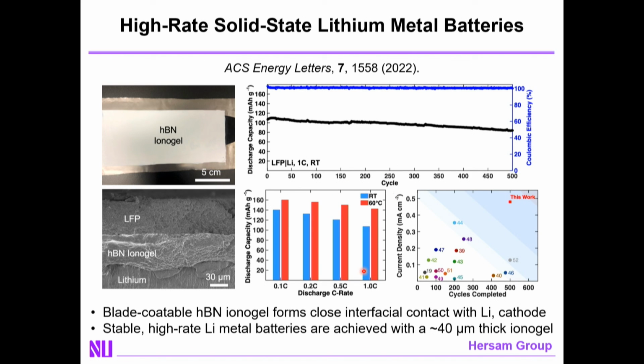This allows you to blade coat whatever electrode you like, including pure lithium. Because it goes down as a viscous slurry, it will conform to rough surfaces, which gives you good conformal contact. Upon evaporation of the solvent, you get strong gelation, therefore you get strong lithium dendrite growth suppression, allowing you to go to high current densities with high cycle life.